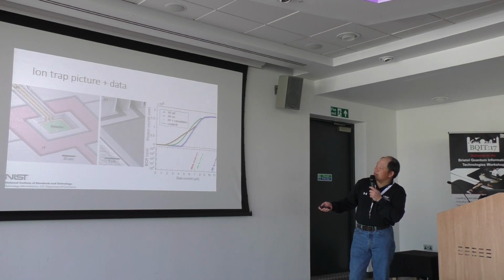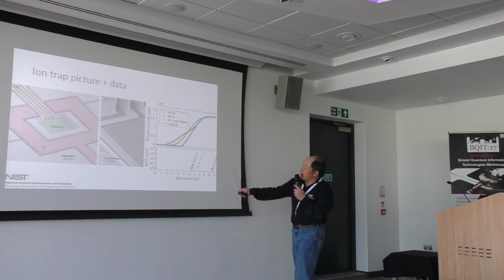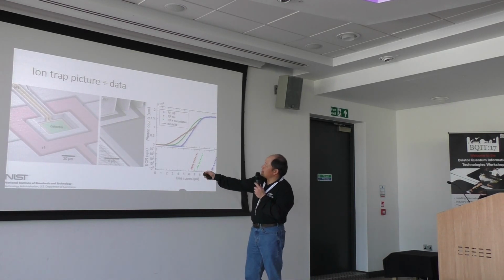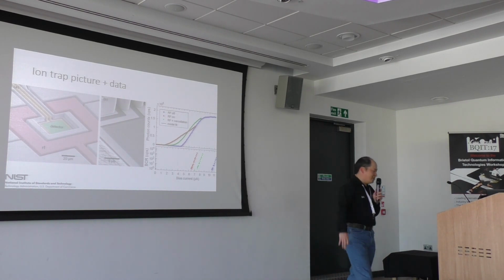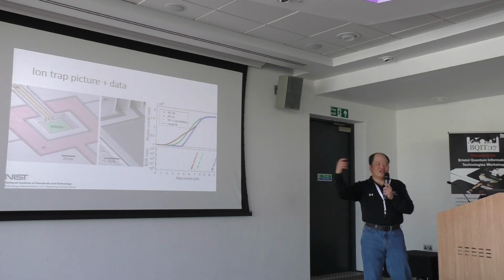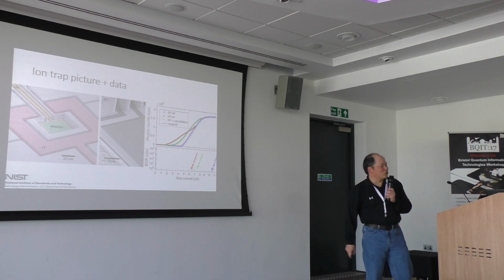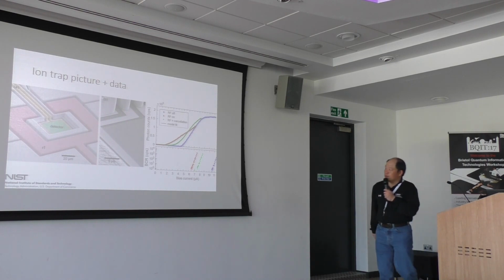So our nanowire detector is in here. It's in green. The RF electrode, which is a potential source of problems, which I'll describe in this curve, is in pink. And then these gold colored wires are actually the leads. And so this is the nanowire. This is the blow up of this region. This is the nanowire. This is the gold electrodes as we normally deposit. And then this is electroplated gold that's used when fabricating the ion trap. So it's a complicated fabrication process where we go in the clean room, make our detectors, and then it comes out of the clean room, it goes into a plating shop where they literally put electroplated gold on top of everything we've done in the clean room to try to integrate the ion trap structure with our nanowire detector.